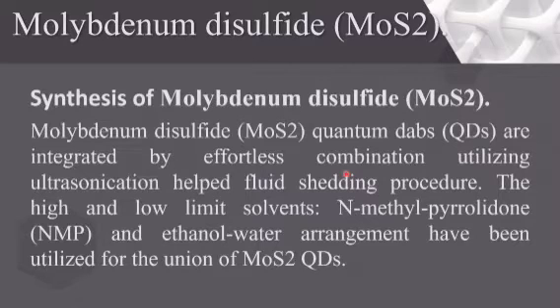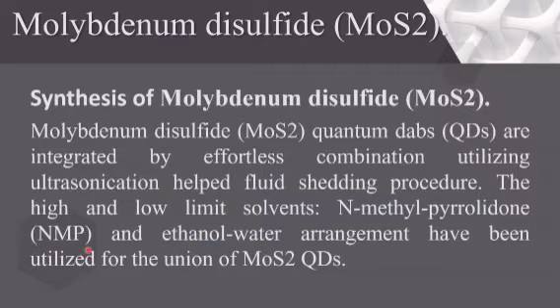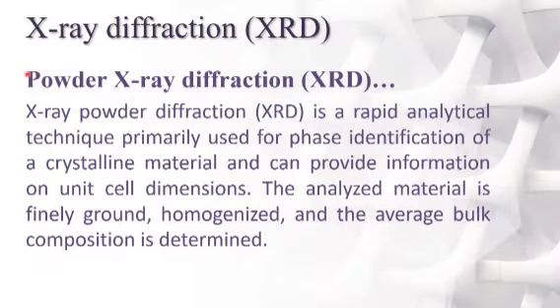For synthesis of molybdenum disulfide, molybdenum disulfide quantum dots are synthesized by a simple combination using ultra-sonication-assisted liquid-phase exfoliation. High and low boiling point solvents — NMP and ethanol-water solution — have been utilized for synthesis of molybdenum disulfide. So far, we have seen how to prepare the metal oxides; now we will see advanced techniques for the characterization of nanostructured materials.